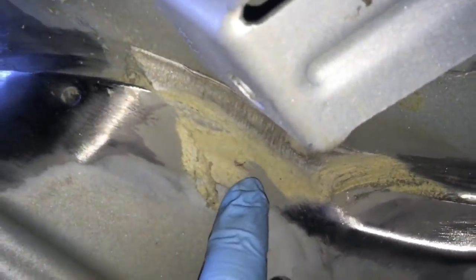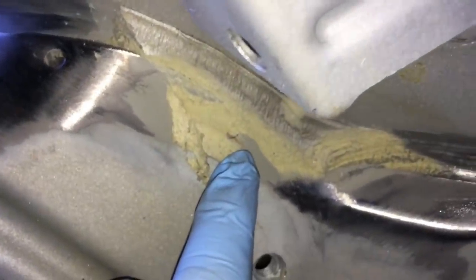Whereas when you come to this one, already I've got a trace of corrosion, and this is a thick seam sealer, so the only way corrosion is in there is coming from behind, and if it comes from behind it's normally because of a crack around the spot weld. So it looks like we've definitely got 2 spot weld cracks on the seat panel, as well as the movement within the rear axle carrier panel up on the corner section.